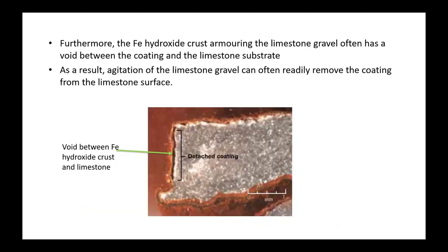Next slide. The other thing that Silvana found was that the ferric hydroxide crust armouring the limestone is not necessarily very strongly bonded. And often in her experiments, there was a void between the crust and the limestone. What that means is if you agitate the gravel, you can break up the crust to some extent and expose the limestone so it can start neutralising all over again. This is relatively straightforward, particularly for open limestone drains, where you can put a bulldozer down the channel with its tines down and agitate the limestone, break off the crust, and get the drain working again. Next slide.